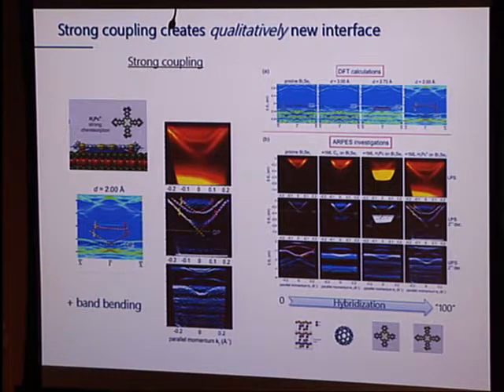And when you look at this and you've seen structures like this before, you realize that this is a case of Rashba splitting. And Rashba splitting is just spin orbit coupling in the condensed phase. And what happens is that you still have your Dirac cone, but in addition, you now have a new set of bands that appear that are split. And they are displaced from each other in k-space, and that's the hallmark of the Rashba splitting. So we know that those are spin-polarized.